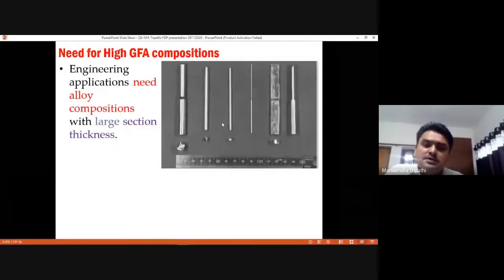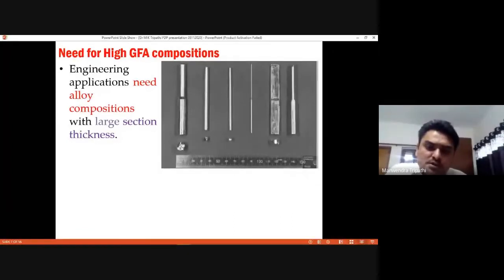The point is that if you cut these rods, you can do optical microscopy or transmission electron microscopy. Obviously, when you quench it, the cooling rate on the surface will be high. So if you cut it and look, on the periphery you will get the glassy structure, but it is quite possible that due to low cooling rate at the center, it may crystallize. So there is a concept of critical diameter for a given alloy composition. What is that? The highest diameter you can make out of that composition so that it does not crystallize at the center.